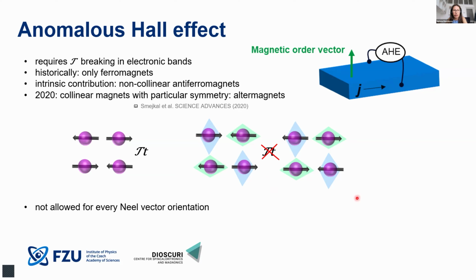So the anomalous Hall effect seems to be a relatively readily available way to test altermagnetism. One more important thing I want to mention is that the anomalous Hall effect in ferromagnets relies in principle only on the orientation of the spin. So once I fulfill the correct geometry, perpendicular to each other, I will always get an anomalous Hall signal. In the altermagnets, it's not only the spin orientation, but also the crystal orientation which matters.